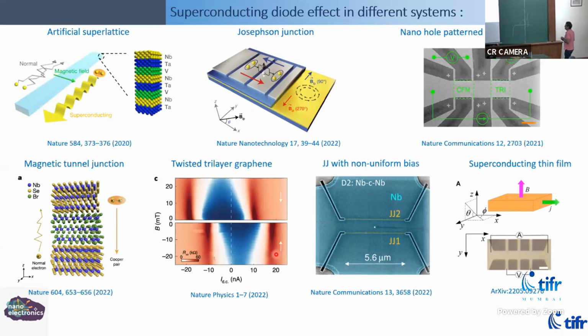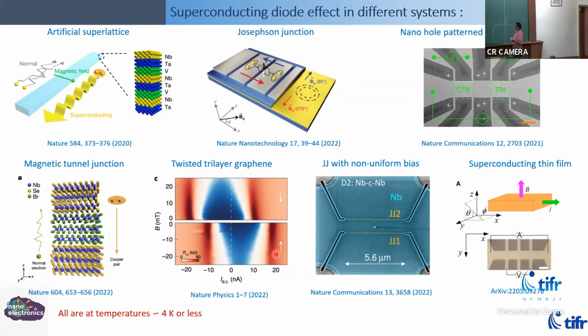So there are some microscopic things that we are still working on. People have been looking at these for fundamental physics as well as technology. People have been looking at the superconducting diode effect in a large variety of systems. And before our work, these were all at 4 Kelvin or less with asymmetries which are of the order of 10%. And we demonstrated and explained that we can see these asymmetries right up to liquid nitrogen temperature. For cryogenics and application, liquid nitrogen is an important temperature, because liquid nitrogen is technologically very easy to access. And we also showed that you can get very large asymmetries in these kind of systems.